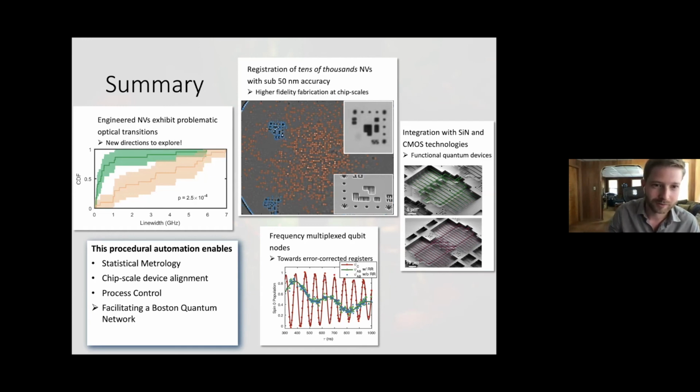Now, the other thing I want to mention is the thing that we actually put in these is not a nitrogen vacancy. This was using a silicon vacancy. We've also experimented with germanium vacancies. And I think we're still going down the periodic table there. And those have fantastic optical qualities in that when we implant them, even our implanted centers look very nice. And they don't suffer as much as a nitrogen vacancy does due to some symmetry arguments of what the defect actually looks like. But their electron spin is quite bad.